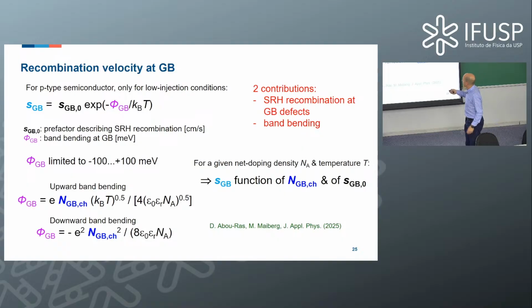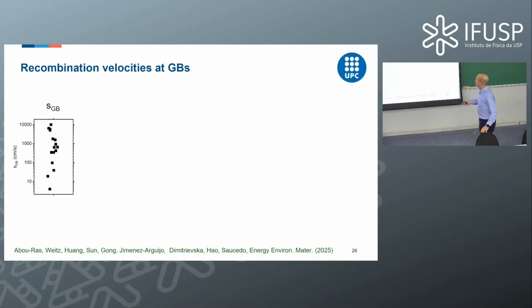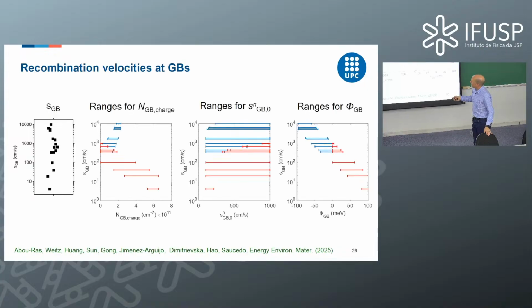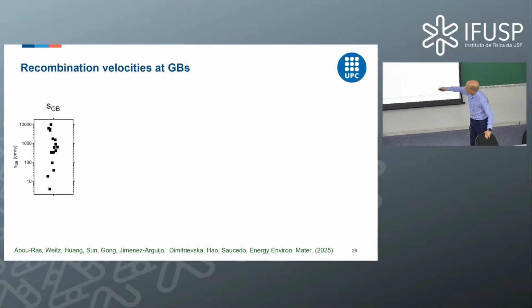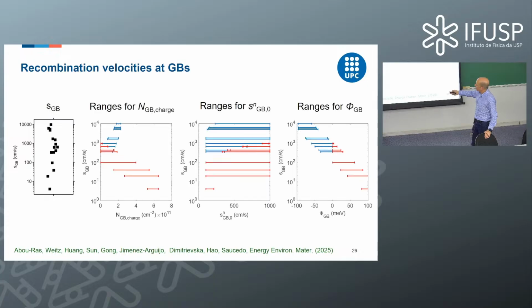And you understand immediately, okay, we have two unknowns for one measured quantity. Of course, we cannot determine these quantities very precisely, but we can give ranges. And this is only one example of a measured data set for one of these samples that you saw. You can see that the corresponding ranges are in blue for downward band bending and in red for upward band bending, given for various values here.